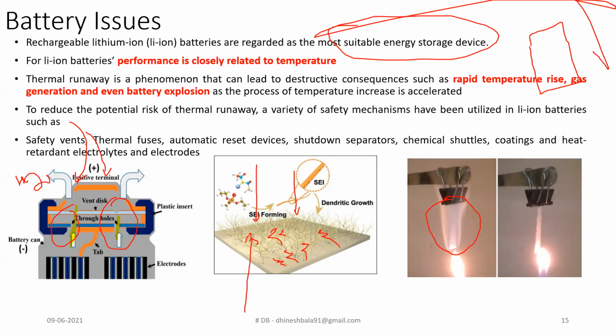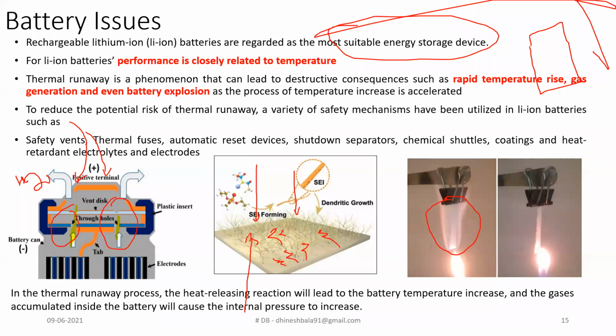So that is one of the main reasons why they suggest charging your battery to 100% before the first usage. That means you are pushing all the lithium ions in the horizontal direction and allowing them to react with the electrolyte and form a strong solid electrolyte layer on the outer side of the electrode. In the thermal runaway process, the heat releasing reaction will let the battery temperature increase, and gas accumulation in the battery will cause the internal pressure to increase. So these are the major battery issues that actually happen when dealing with lithium-ion batteries.